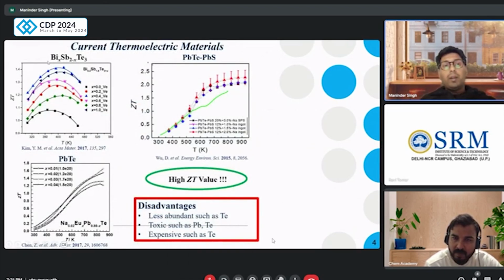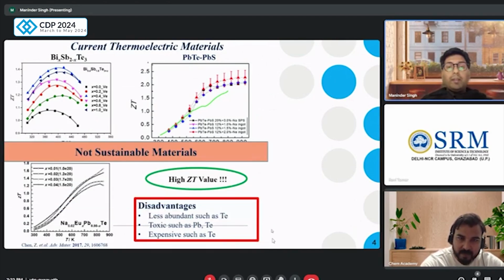The current thermoelectric materials were formed by bismuth antimony telluride, lead telluride, and lead sulfide, and they had a high ZT value. But the thing is, we have to create a sustainable thermoelectric material. The problem with the existing thermoelectric materials was that tellurium is less abundant, and the toxicity of lead and tellurium is also high. And tellurium is expensive as well. So we need to create a material which can be used for a sustainable ecosystem. So we can consider them not sustainable materials.